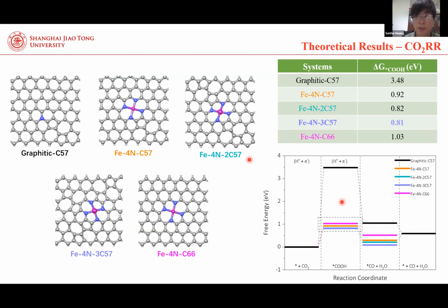The graphene system with 5 and 7 defects shows bad performance with a free energy gap of 3.48 eV. After introducing the iron nitrogen 4 sites, the free energy of the rate limiting step sharply decreases. By comparing with the system without defects, we can also notice that the system with 5 and 7 defects possesses a lower free energy gap. Interestingly, when the number of the 5 and 7 defects increases, the free energy will be lower. The system with 3, 5, 7 defects and the iron nitrogen 4 sites shows the lowest free energy of 0.81 eV.